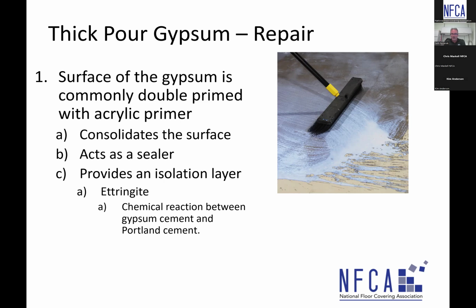And it creates a little bit of a stress right at the surface that can cause failure right at the surface. So it's very critical to have a double prime with an acrylic type primer that creates that isolation layer between the new patching or leveling material and the existing gypsum. But check with your manufacturers on their recommendations. I just wanted to point that out to everybody.